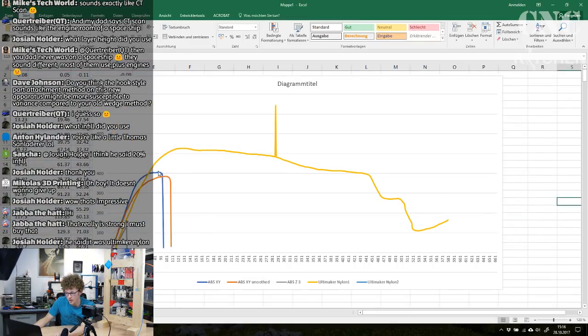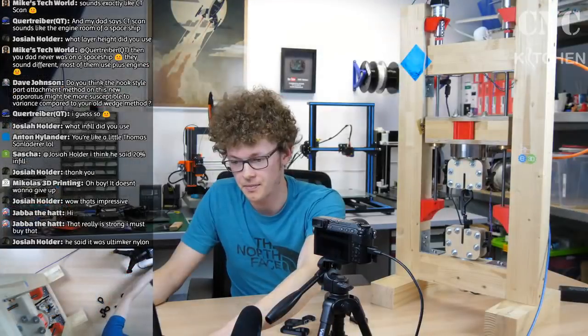So these two lines were our ABS. This one was the ABS, which was printed straight upwards in Z direction. The nylon was doing really well up to this point. So we have like 20-25% more load which the hook was able to bear, and then it started yielding, and at these points right here you can see where the crack started up till the end where it really failed, and then I stopped the test. Okay, let's get back to our, come on, there we go.